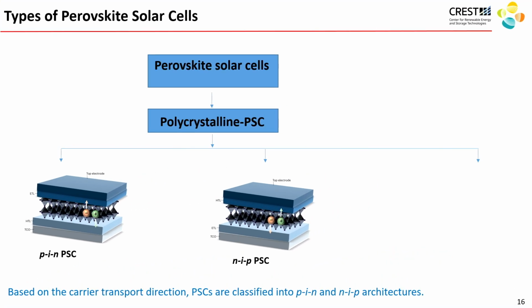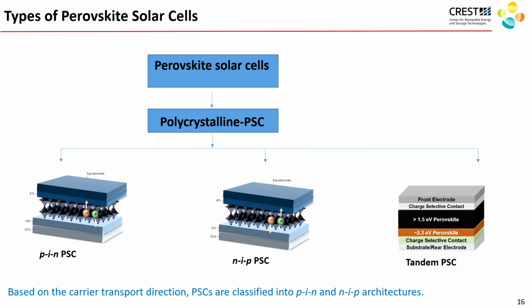If you look at the perovskite field, there's typically 3 types of device configurations. One of them is called PIN, where the hole transport layer is closer to the transparent oxide layer, and the electron transport layer is on the other side. And you have the NIP, where the electron transport layer is closer to the transparent conducting oxide. And then you have single crystal devices as well, and tandem devices that combine multiple layers of perovskites of different band gaps to collect photons of different energies more efficiently.